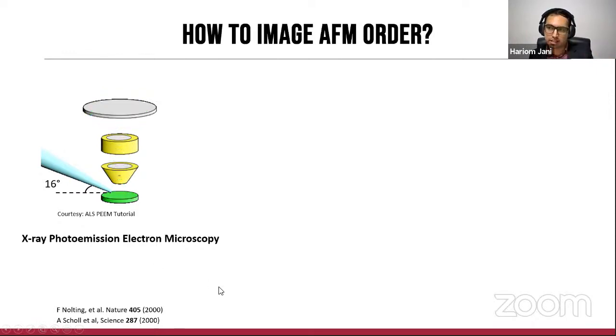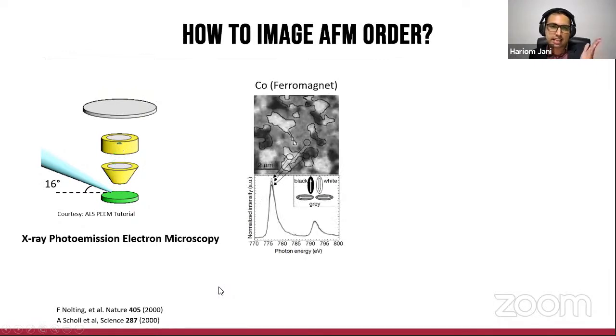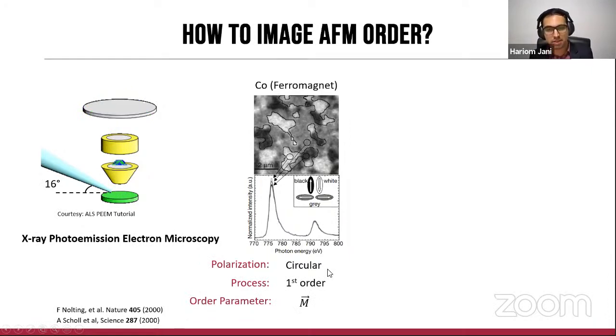But the key point that I would like to highlight here is that as opposed to a ferromagnetic case, which involves imaging at the main edge, for example, let's say we have a cobalt coupled to an antiferromagnet that I'm just going to show here in very early PEEM work. The ferromagnetic order can be mapped with circular dichroism. It's a first order process, and therefore we are able to directly map the magnetization.